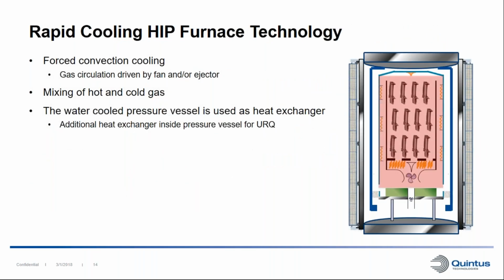If we're looking closer at the technology and how we actually can achieve these high cooling rates in the HIP system, on the right here we have a schematic picture of a hot HIP unit, which is the pressure vessel and the furnace. So we have the pressure vessel here, and the pressure vessel is water cooled. Both the cylinder and the upper and lower closure have water cooling channels. And then inside the pressure vessel, we have the furnace. And in the center of the furnace, we have the hot zone. That's where we put our parts that we're processing, and that's where we have the high temperature.